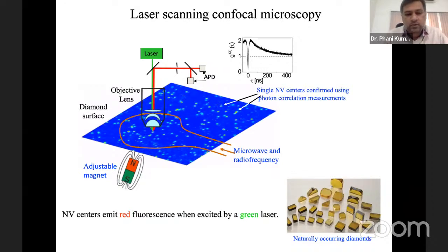The optical setup we use is that we send this laser light through an objective lens, and this will excite the NVs. The fluorescence emitted by the NVs, which is in the red wavelength region, is collected back through the same objective lens and sent to a single photon counting module. And we can probe the spin properties of these NV centers using a magnet and also microwaves.